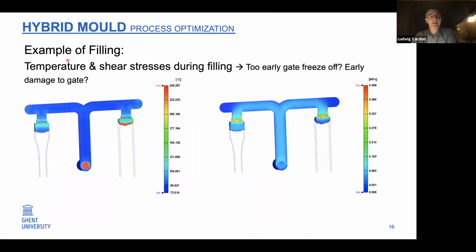So why is this important? Well, with this kind of hybrid molds, the temperature and shear stress during the filling you can fully investigate by modeling, but you can also analyze that by experimental investigation. That's what we try to investigate, and we also try to reduce the injection pressure in that manner. Because when you have a plastic mold and you inject plastic in plastic, the plastic will not solidify. This means the injection pressure you need is a lot lower, which also has an effect on your shear stress, and lower injection pressures can be applied.